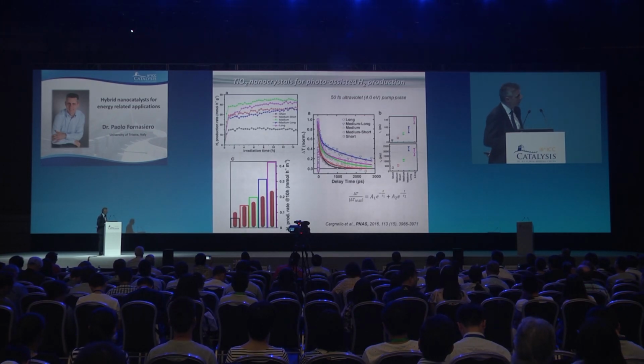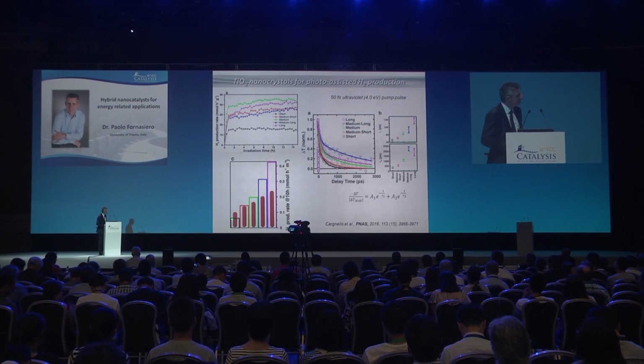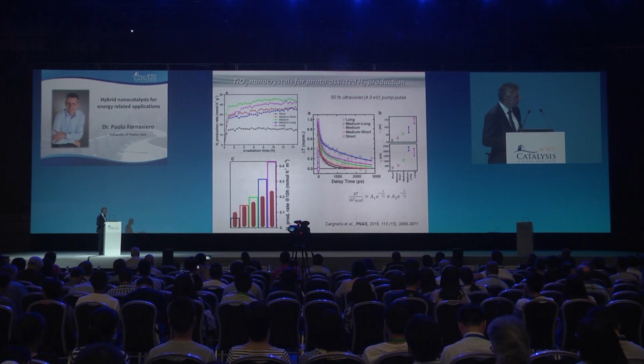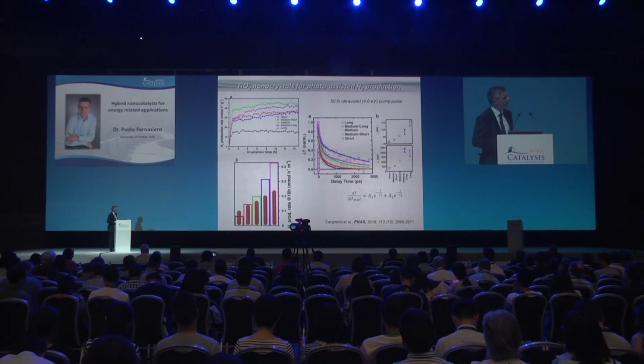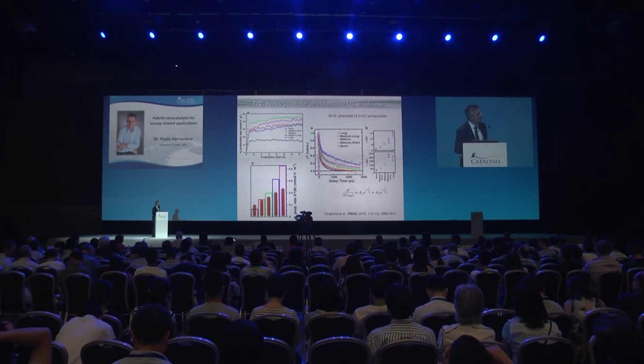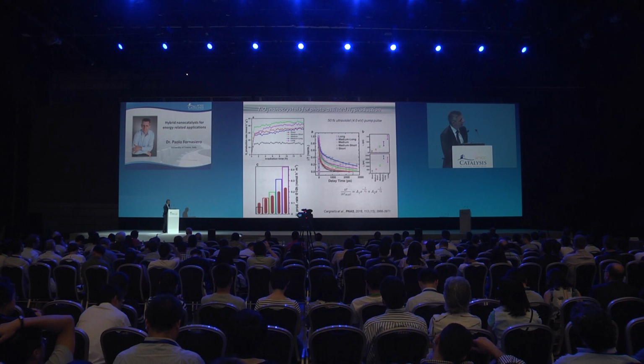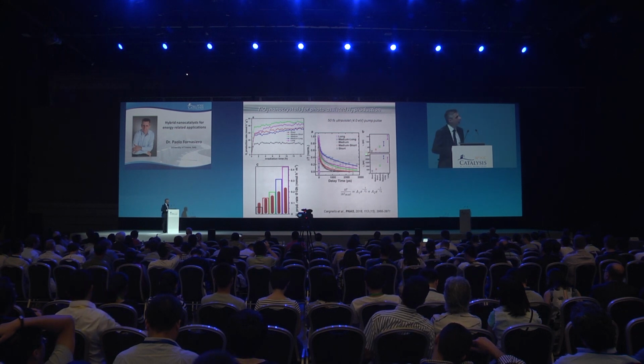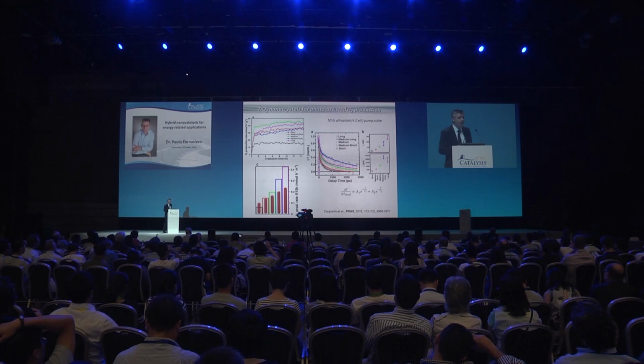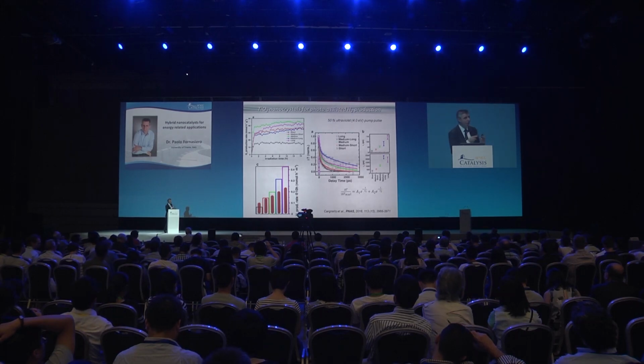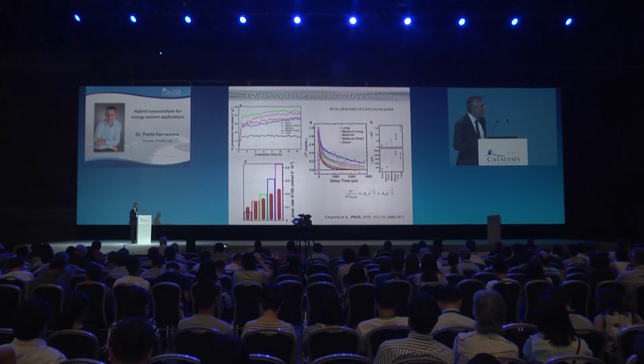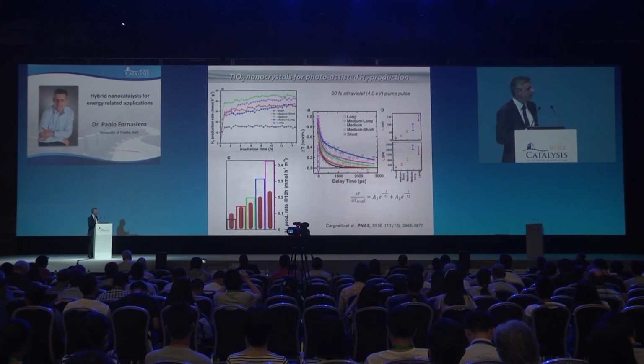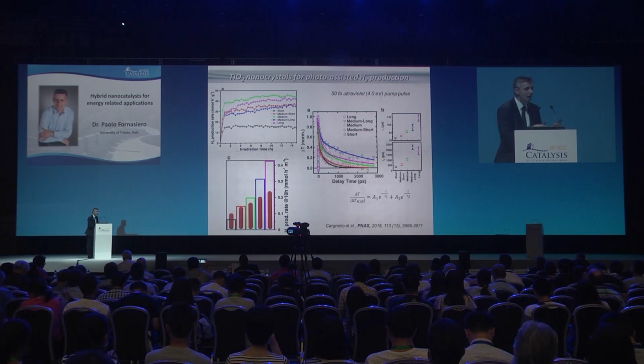And the results were very interesting, in the sense that the amount of hydrogen you get strongly depends on the length of these nanorods, even normalizing by the surface area, as you have to do. And this is related to the fact, as we proved by EPR and fast transient absorption spectroscopy, that you significantly enhance the lifetime of electron holes by playing with the anisotropy of this nanocrystal. So we do believe that this is a general approach to enhance the photocatalytic activity.